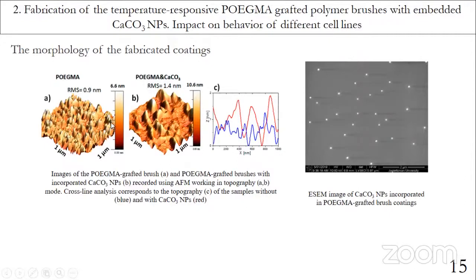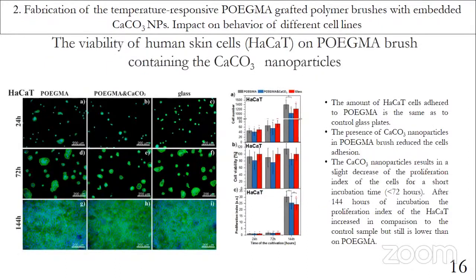Incorporation of the calcium carbonate strongly transforms the structure of the coating from relatively smooth to more structured, well expressed at large elevations. An impact of the low concentration of the embedded calcium carbonate nanoparticles on cell adhesion and growth depends strongly on the type of studied cell line.